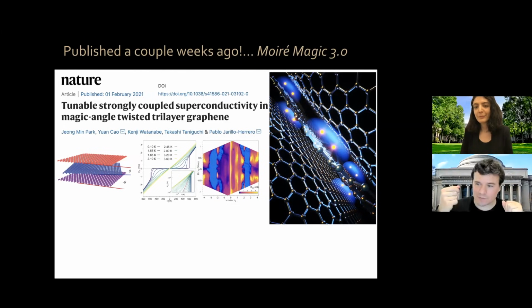Now, in addition, on top of that, you can actually strain the lattices, okay? And in fact, these two-dimensional materials allow you to do something which is almost impossible to do in bulk crystals, which is to apply heterostrain, a different amount of strain to one layer with respect to the other. And theorists are now calculating all these possibilities. What happens when you strain magic angle graphene? What happens when you apply heterostrain? Very interesting things happen, okay? The different phases of matter that magic angle graphene can exhibit can change as a function of strain, okay?